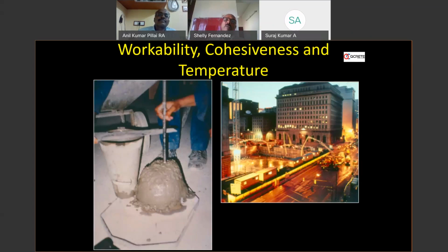That is, if you are given an order for 100 mm workability, it can vary from 75 to 125, actually. So there will not be any rejections. Then, whether the concrete produced by the operator is cohesive or not, you can see just by looking: the entire workable concrete is covered with cement paste, and proper slump is there. The temperature of concrete can also be measured here, before pouring into the structure.